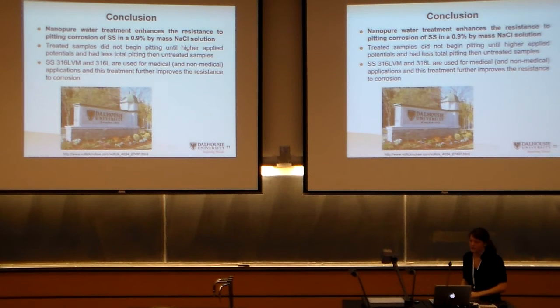So I'd just like to conclude by saying that this water treatment in nanopure water has improved the corrosion resistance of our stainless steel samples in sodium chloride solution. We've seen overall that the treated samples have shown a lot fewer pitting events, as well as they don't pit until much higher potentials, and they showed great improvements compared to our untreated samples.